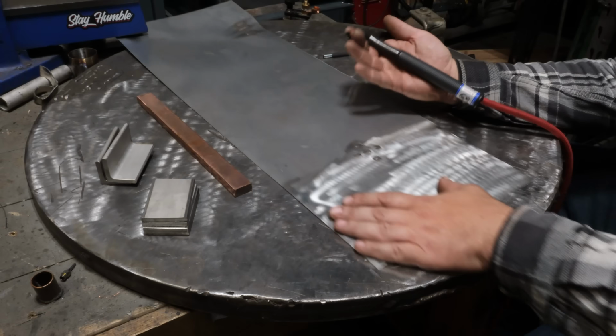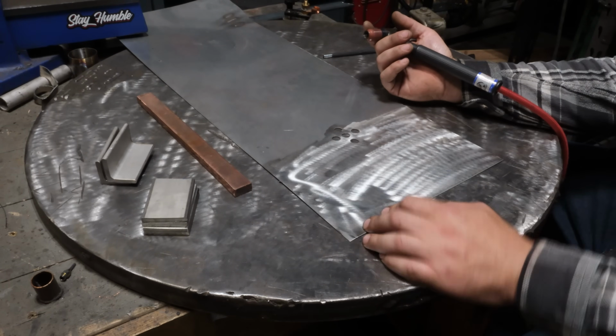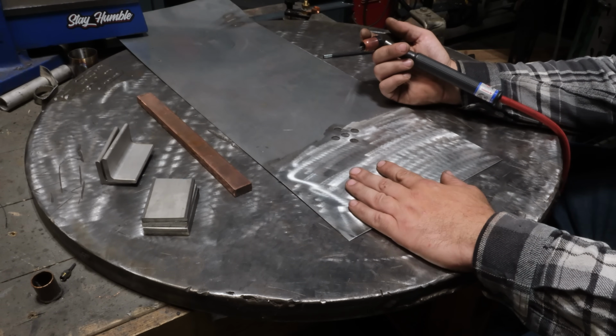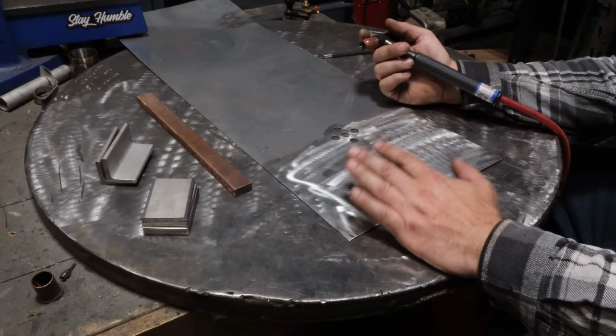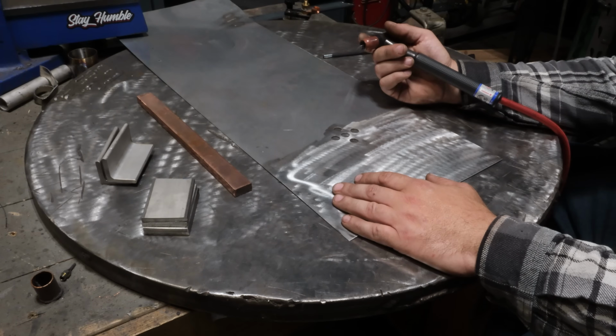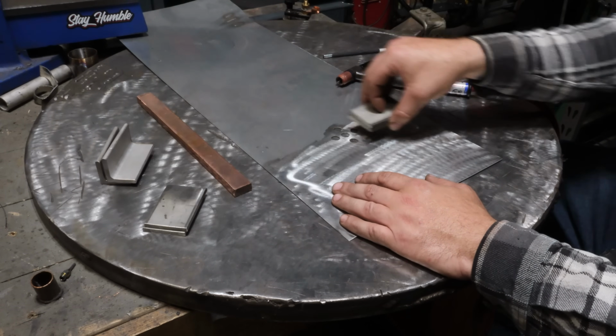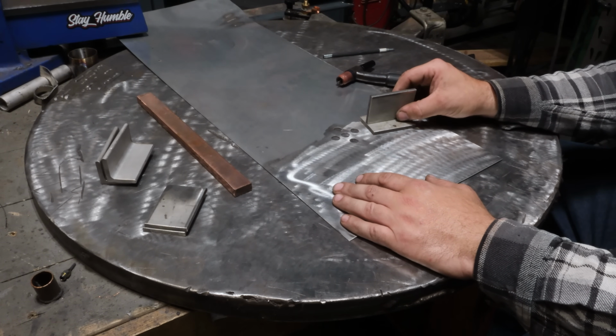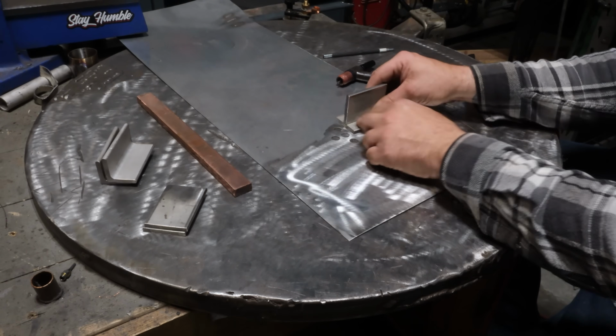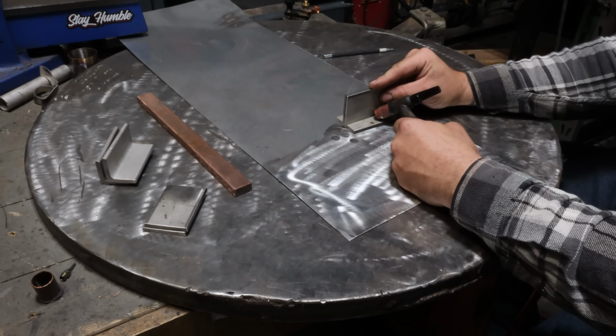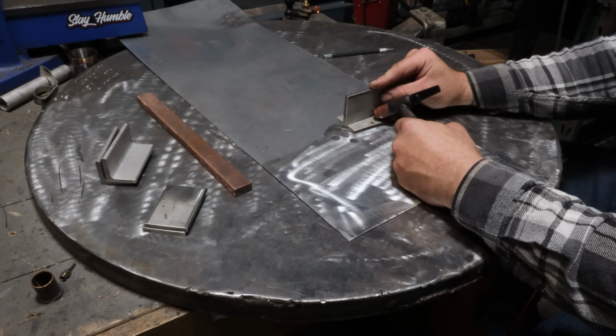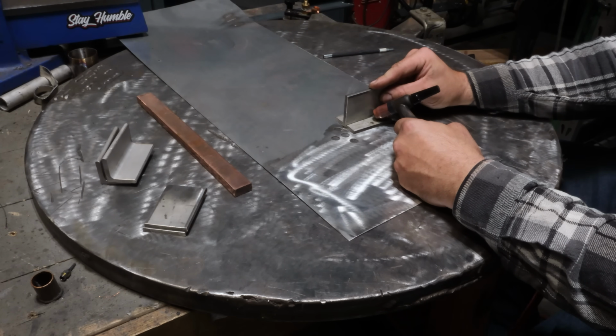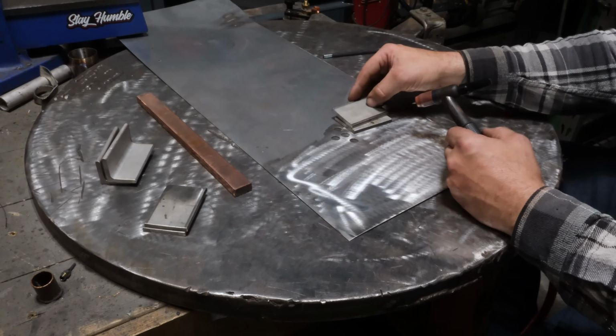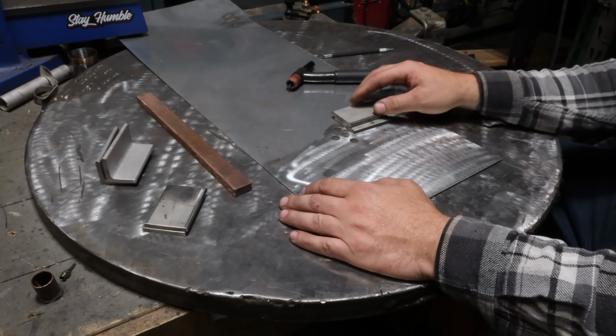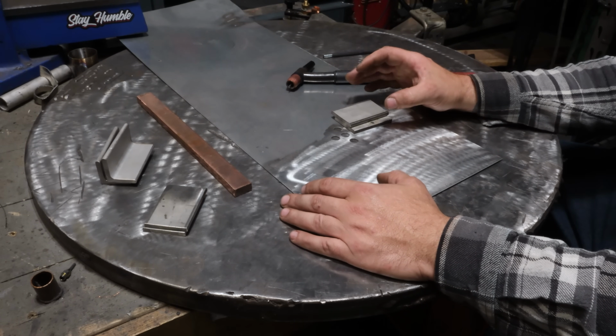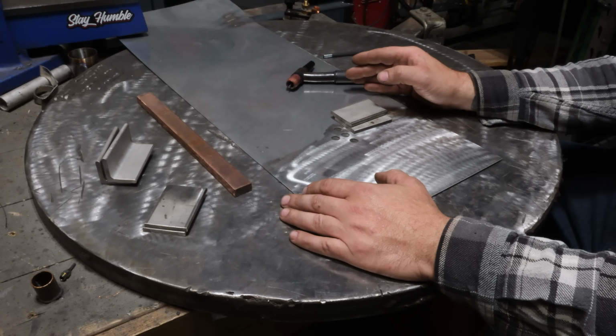And a great example would be this super thin sheet metal here. Generally, you're going to need a fairly big cup in the flat position because nothing is trapping argon. When you go and weld, say, a fillet weld or a T-joint, where you have the plates like this, your cup being down here in the corner more or less forces argon out and protects the weld a lot better because it's trapped. Remember guys, argon is heavier than air. Therefore, if you have some method of trapping it, you can get by with a smaller cup typically.